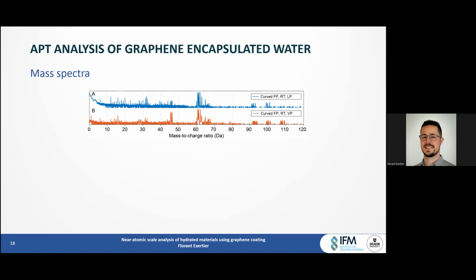And also, there appears to be fewer peaks for the voltage pulsed experiment, which can be explained by the higher field, which causes evaporation as lighter ions due to field-induced molecular ion dissociation.